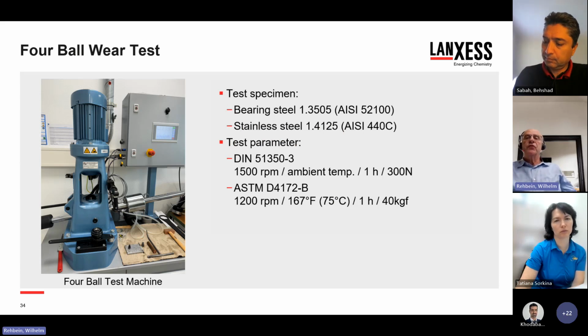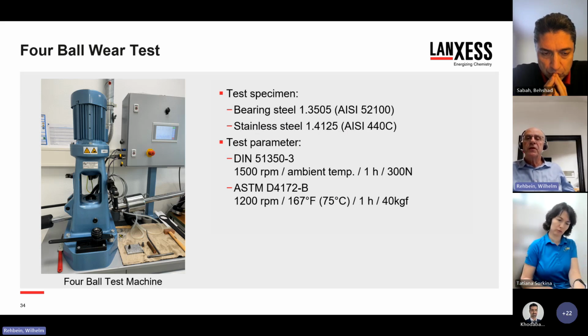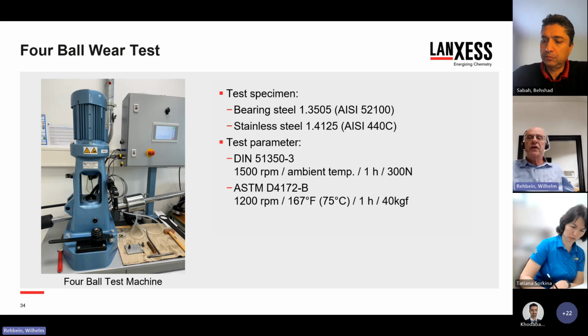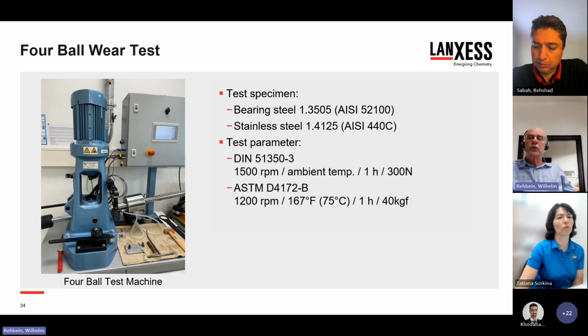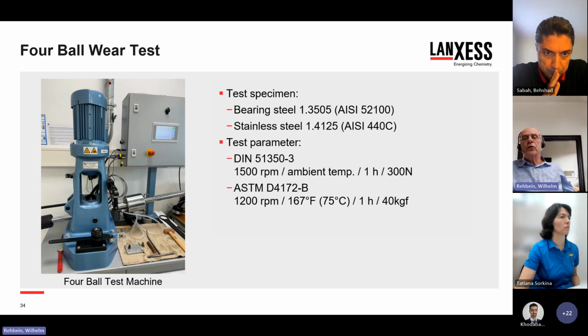But because the tapping torque test does not give a direct indication about tool wear, we additionally used the 4-ball wear test to evaluate the influence of the EP additives on wear in this kind of mixed lubrication regime. And we ran the test with the standard, which is ball bearing steel, as well as with stainless steel balls. And the test conditions were according to ASTM D4172B, but also according to DIN 51350-3.